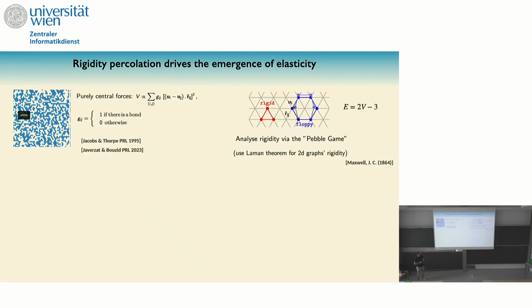And the idea is to count how many constraints I have in my cluster versus how many degrees of freedom I have, right? So I have edges, I have vertices. Each vertex has 2 degrees of freedom, and each edge would add a constraint in my material. So the minimal rigid object in this dimension that you can form is this one, where you have 3 vertices and 3 edges.